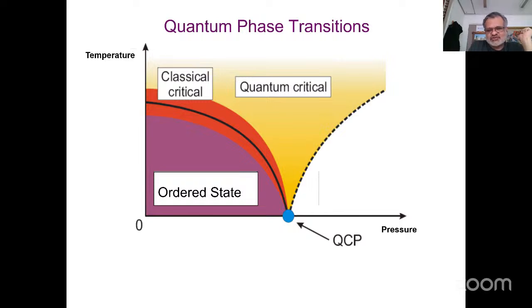And as it approaches that critical point, as it's called, the ordered state starts to fluctuate and starts to interact, if you have a metallic system with electrons in the system. What you're effectively doing is squeezing all that entropy into that corner of the phase diagram here near the critical point, which makes many of the states thermodynamically equivalent, and you cannot easily predict by standard methods what could emerge from that. And that's what guides us into the story.